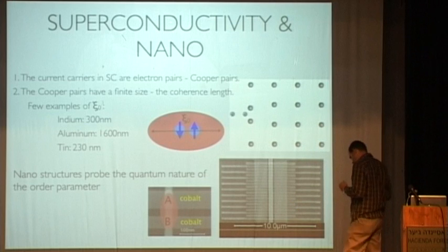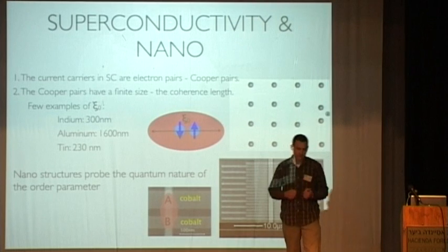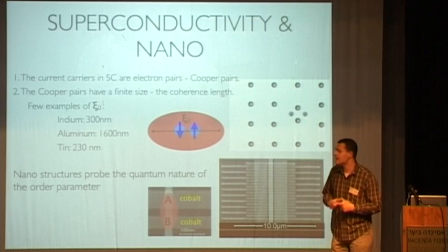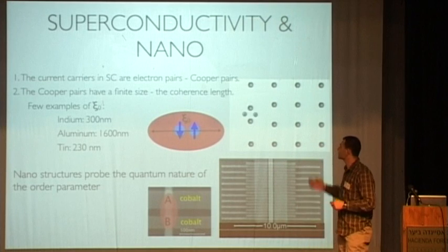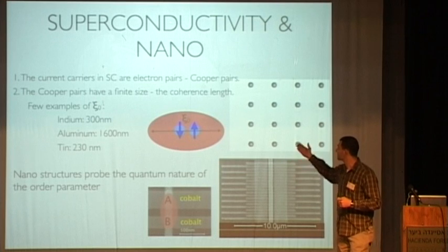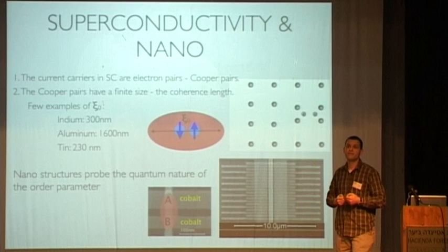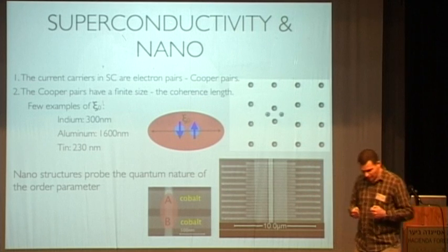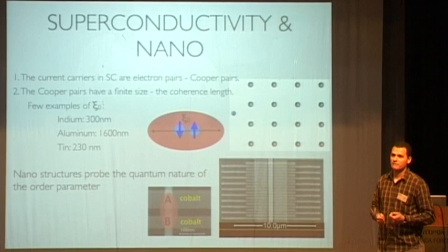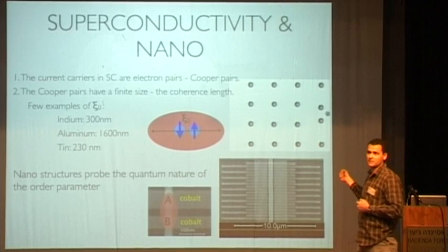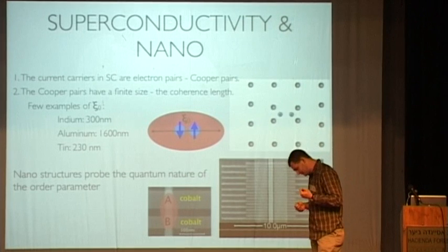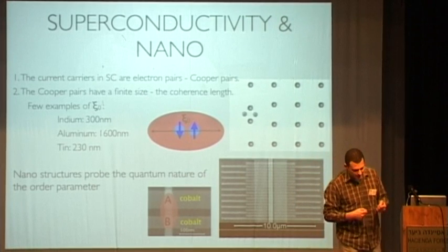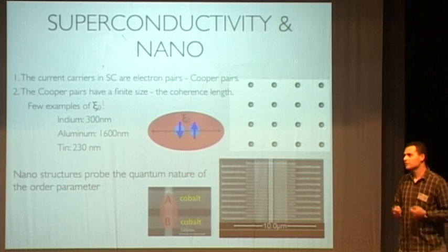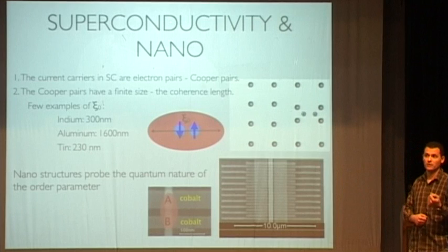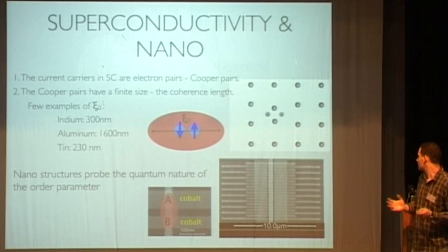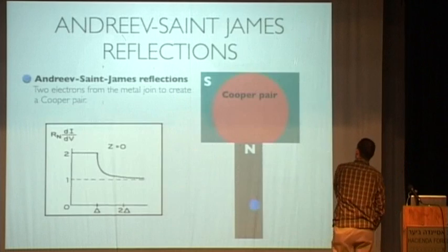And this immediately gives us a property of the elementary particle, which is that it has a finite size. And this size can be quite large, at least for type 1 superconductors. You can see here, indium, for example, is 300 nanometer, aluminum is 1.5 micron. And this is important to us because we are able to produce nanostructures, very small, which are smaller than this elementary particle, which gives us a tool to measure this quantum creature, and a tool to measure how this pairing, how this mechanism of superconductivity really works. So this is the motivation and why nano is so important.